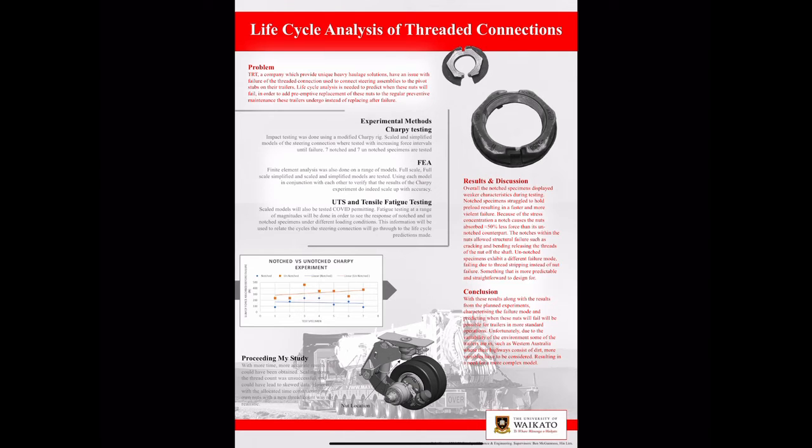It was found that unnotched specimens could absorb approximately 50% more force than the notched counterparts. Another discovery was that the notched samples struggled to hold their preload, often after one impact losing torque, resulting in a much more violent failure.